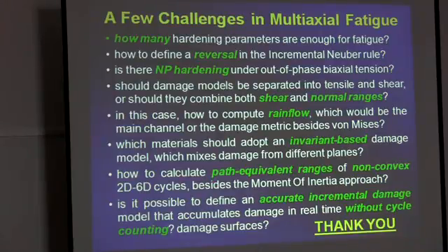How do you calculate equivalent ranges of non-convex cycles? I mean, we use the moment of inertia method, but also all the other methods, even Novozhilov's integral and the convex enclosure methods, can only deal with convex paths. They don't work very well with non-convex ones.